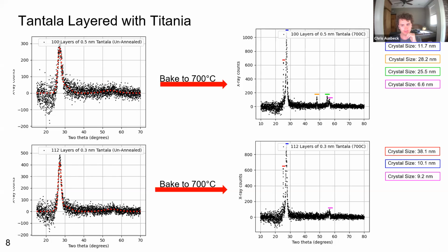Yes, it definitely depends on the sample. Usually the thicker samples tend to crystallize all at once. And then the thinner samples, the ones with smaller nanolayers, tend to crystallize much slower. Tantala in specific seems to crystallize very quickly. Tantala layer with titania, there was definitely much slower crystallization, happened over around 150 C, a range around that large.